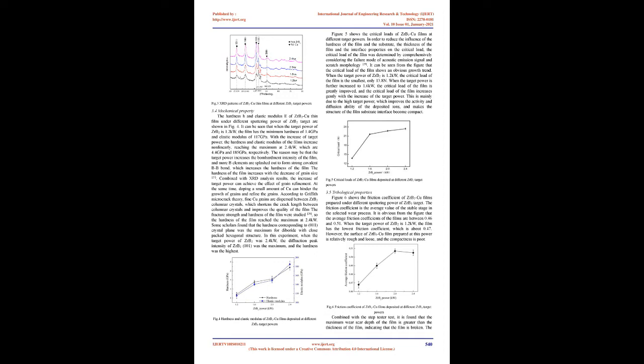The reason may be that, on the one hand, under the condition of constant temperature, bias voltage, and working pressure, the gradually increasing target power improves the bombardment effect of incident ions on the film, thus improving the particle size and flatness of the film surface. On the other hand, as a soft metal, Cu has a certain effect on the grain growth. Wei Chunbei et al. [22] found that when the content of Cu is high, it is easy to aggregate. Therefore, the surface roughness of ZrB2 films is related to the relatively high content of Cu in the films when the target power is small.